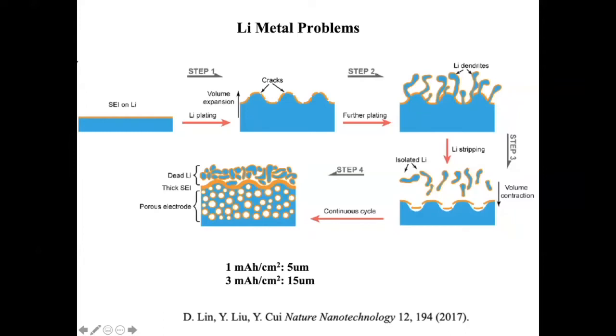During this plating process, lithium reacts with electrolyte forming this SEI, and this plating causes a volume change. It's going to break your SEI somewhere because the plating will not be layer by layer uniformly. You can nucleate the hotspot and grow out this dendritic structure, this filamentary structure. During stripping, it's not uniformly stripped, right? You cause the dead lithium formation. Before long, your battery will lose its efficiency and die fast. Plus the safety problem, we all understand this.